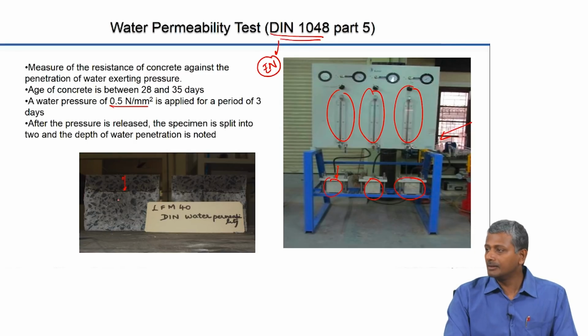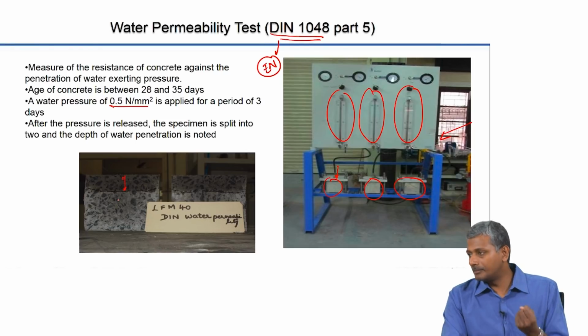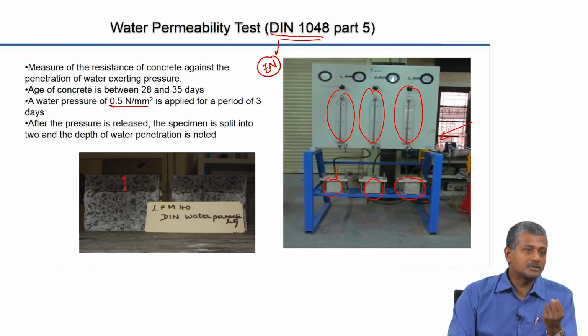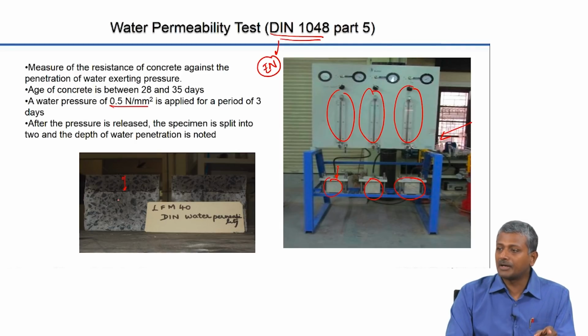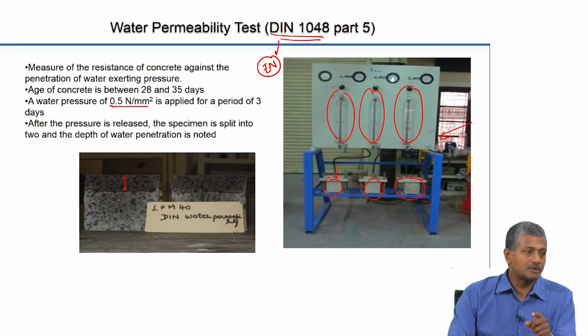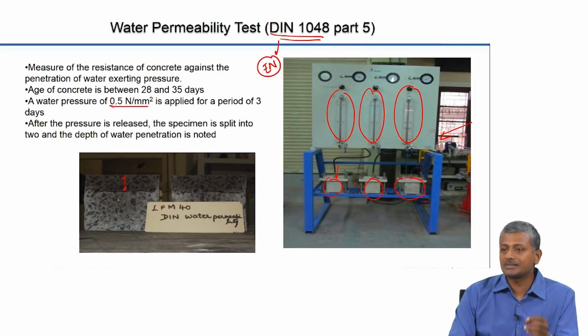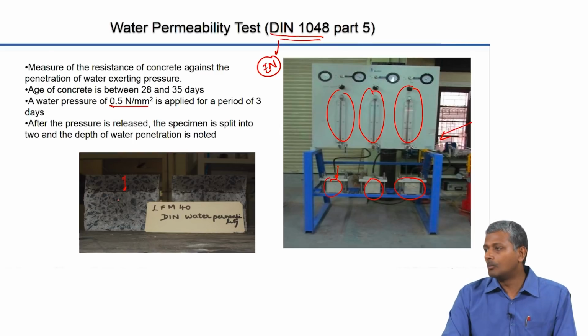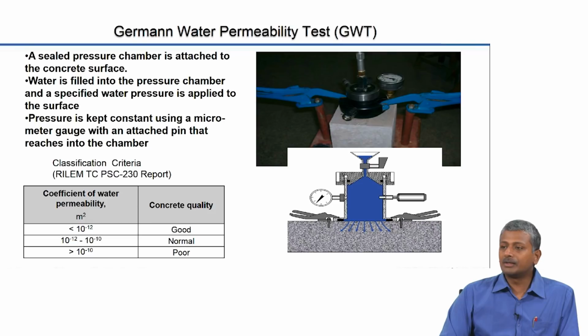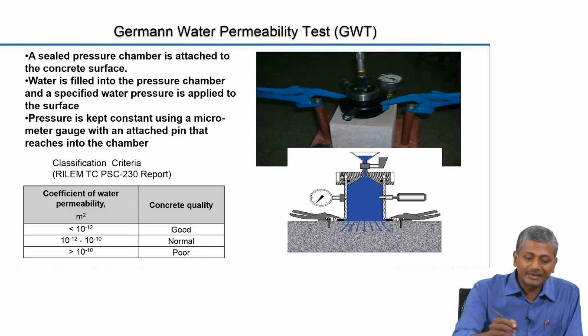Only then we can apply a direct permeation law. Otherwise, what's going to happen? If the concrete is dry, what will it also do? It will absorb, because it's drier than the water, it's going to absorb water, and then you'll have other mechanisms apart from permeation also which are acting in the same experiment. That's the reason why the code specifies that you need to use this concrete in a saturated state directly taken from moist curing.